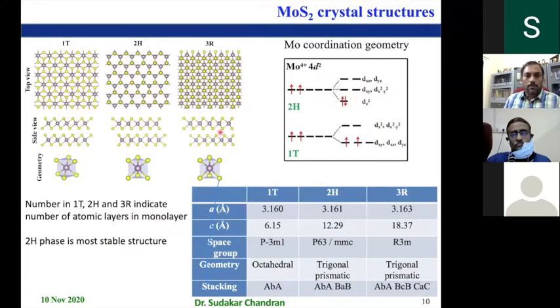Of course, depending on where exactly, in what coordination, the molybdenum sits, you will have a crystal field effect. For example, if it is in the 1T phase, it's a d2 system. Therefore, you will have two unpaired electrons.